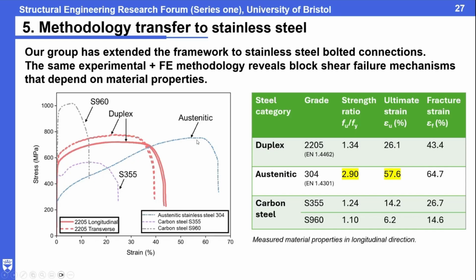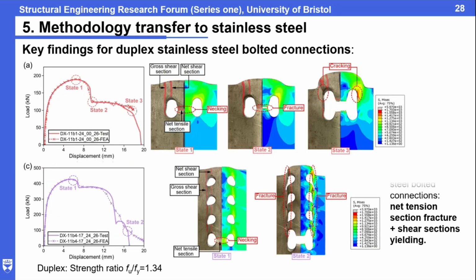They have significant strain hardening. We mentioned that for the shear plane, strain hardening is very important to develop the shear stress level, right? For the duplex, it is similar to the high-strength steel, but the ductility is much higher. It will also affect the structural behavior of the bolted connection made of stainless steel. They will be different. So we followed a similar investigation and found that for the duplex one, the ductility, of course, is larger. And important is the block shear failure mechanism. We want to check whether the philosophy developed based on the high-strength steel can be used. For the duplex one, we found the failure mode is similar. So the philosophy is okay, but we have modified the design equation based on the stainless steel's material property.